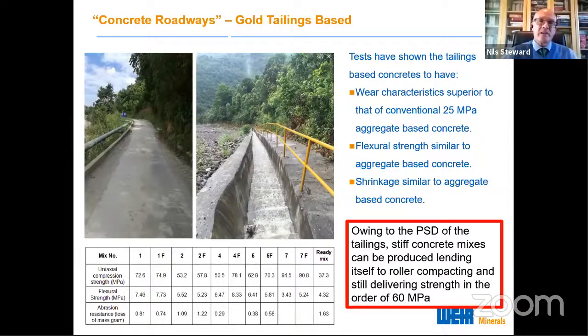The wear characteristics of this product were superior to the equivalent 25 MPa aggregate-based concrete. A lot of this had to do with the aggregate-based concrete: as it wore, the aggregates would pop out of the concrete. In terms of the tailings-based concrete, the aggregates are less than 300 microns in size. So you don't get a great loss, and then that pit that is formed that the rest of the corrosion or erosion can take place in. Flexural strengths were very similar, and shrinkage was very similar to the aggregate-based concretes.